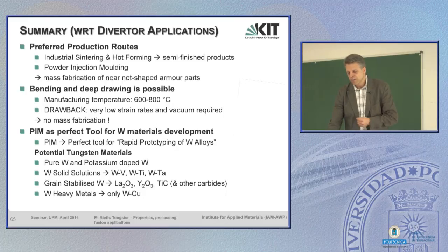Preferred production routes now are industrial sintering and hot forming. That's the only way from industry, but powder injection molding would also be a viable way to mass fabricate at least armour materials or armour parts out of tungsten. Bending and deep drawing is possible. The drawback here is that it goes very slowly, so it certainly is not a mass fabrication method.